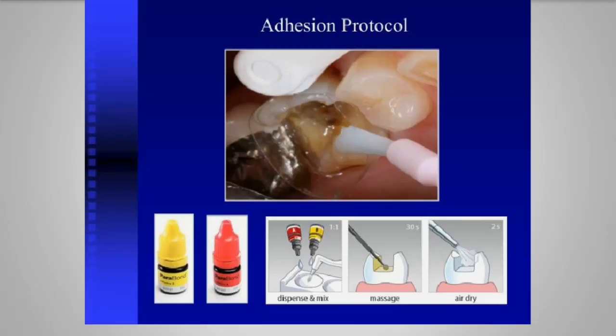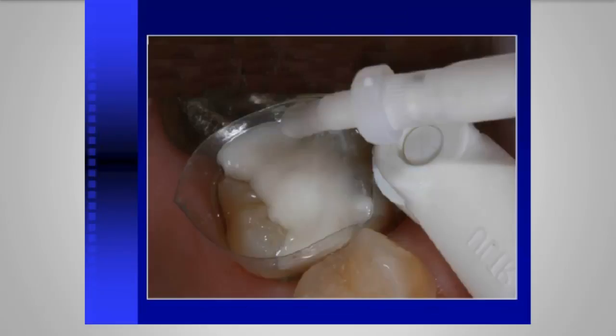at this point. And then what you do is take the cannula and just start at the gingival box, go back and forth, keep the cannula under the composite material, and don't take it out. You may introduce air voids, go back and forth, back and forth. Actually, I'm not trying to be funny about this, but this is my sonic fill by moving my hand around here with the cannula of the material. You get 1 minute to do this.